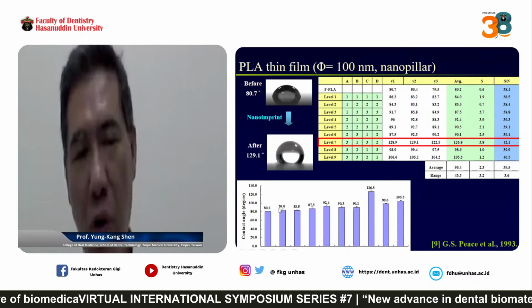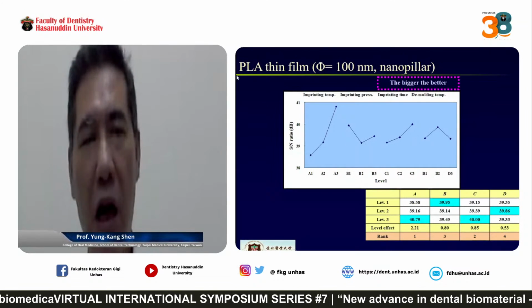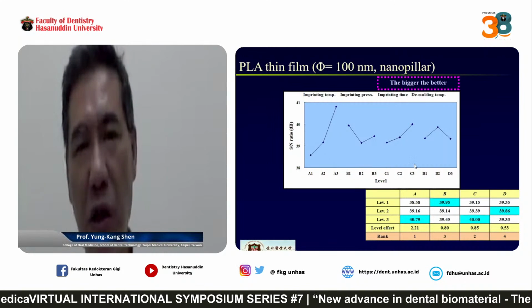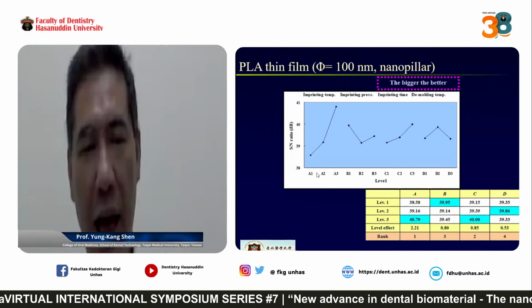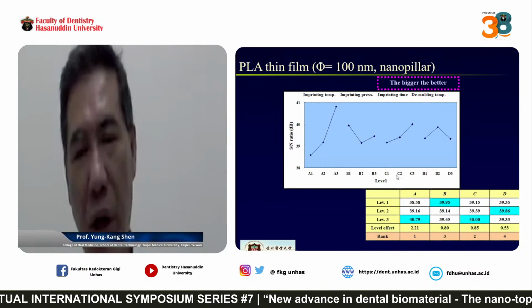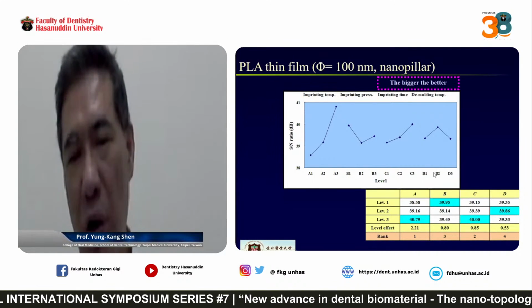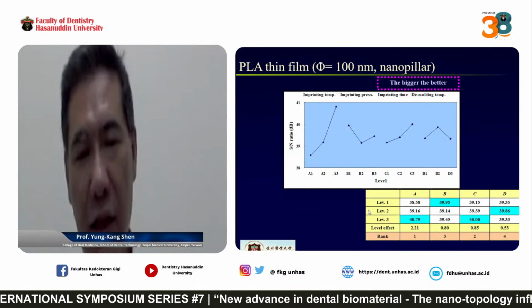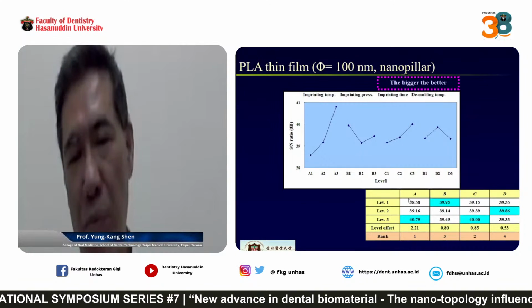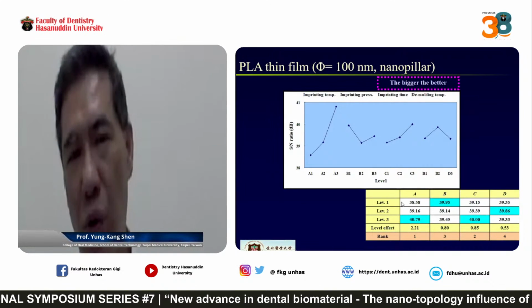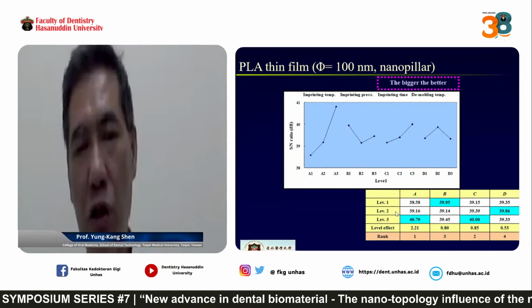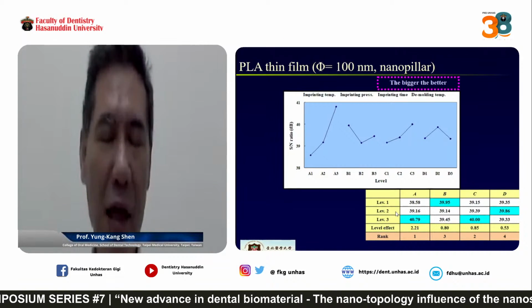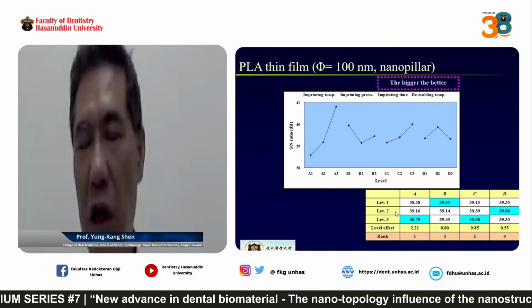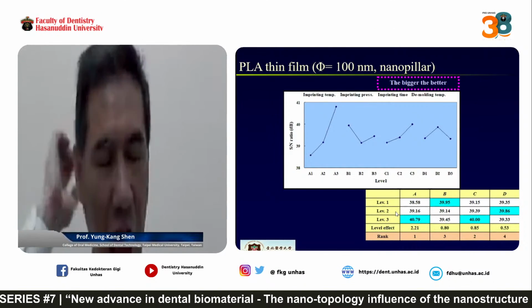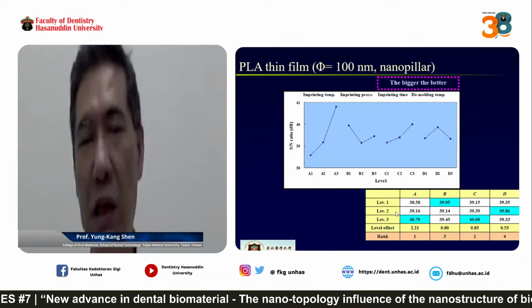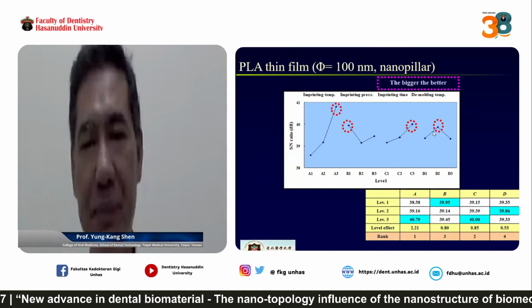This is the L9 table for the different contact angles, also for the PLA thin film with a diameter of 100 nanometers. This is the optimal processing. A is imprinting temperature, B is imprinting pressure, C is imprinting time, D is demolding temperature. Here we can see that imprinting temperature is the most important factor, because this uses the Taguchi table. So if you want to make a nanostructure by the nano imprinting process, you must control the imprinting temperature first. Then you can get a very good nanostructure on the polymer thin film.